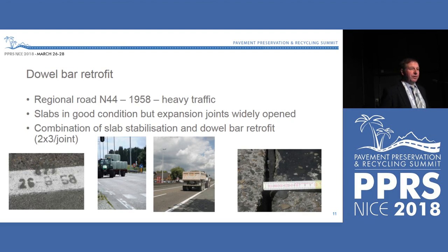Dowels are the smooth steel bars which are used in concrete slabs in order to guarantee the load transfer between the slabs. They also guarantee the driving comfort. Well, for those older pavements, sometimes dowels were not used during construction. It is still possible to insert the dowels when the road is already there. And I give you here a very short case study of a regional road, N44 in Belgium, which was built in 1958. Slabs were quite thick, about something between 25 and 30 centimeters thick. They were long, and as you can see on the two middle pictures, there is quite some heavy traffic on this road, but still those slabs were in very good condition.